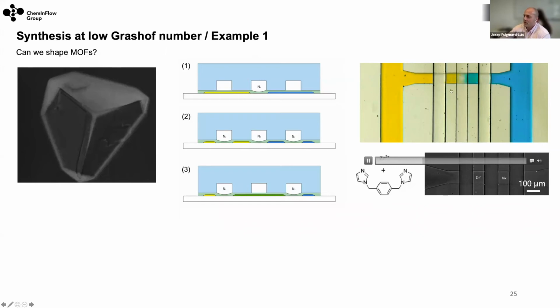And what we can achieve here is what they describe as a free interface diffusion process. So there are no convections occurring there. When I read these papers a long time ago, the group of Professor Stephen Quake at Stanford University were the ones developing this type of microfluidic device, and they were always talking about this free interface diffusion process. They were using this approach to crystallize proteins or big biomolecules that are difficult to crystallize. And to be honest, I was very surprised because during my time at Zurich, I went to Novartis, and they are actually using these kinds of devices to crystallize some of the drugs that they are producing, because it's a free interface diffusion process.